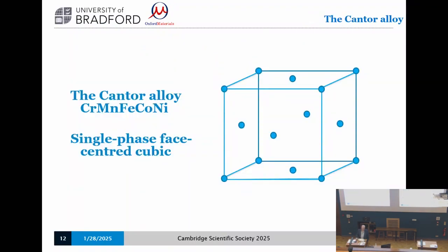This is the Cantor alloy. The Cantor alloy is an equiatomic mixture of chromium, manganese, iron, cobalt, and nickel. We discovered in the middle of that mess of lots of compounds a region which had 5 components in it: chromium, manganese, iron, cobalt, and nickel, with a single simple crystal structure, face-centered cubic.